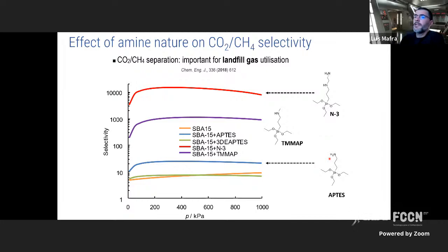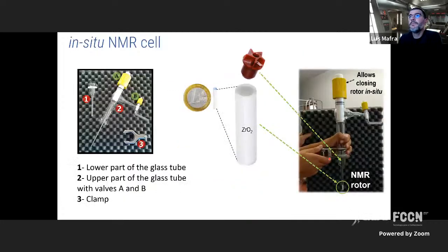So it seems that the bulkiness of the molecule and the basicity of these amines have a drastic influence on the selectivity towards CO2, okay? But why? Can we understand atomic level details that can drive this mechanism? So before showing you some NMR spectra, I should tell you that we have to be very rigorous packing our samples, because if you pack the samples in open air, so this is a typical sample holder, which is a rotor which has more or less 1.5 centimeters height and 3.2 to 4 millimeters of diameter, okay? And you just have to pack the powder inside, you close it with a specific cap, and you have the relative size of the rotor by putting a coin just on the side here.